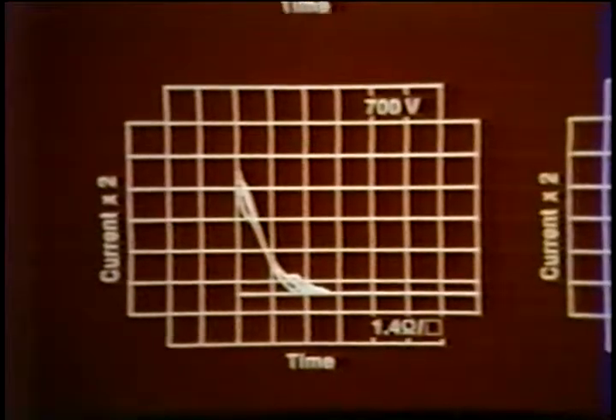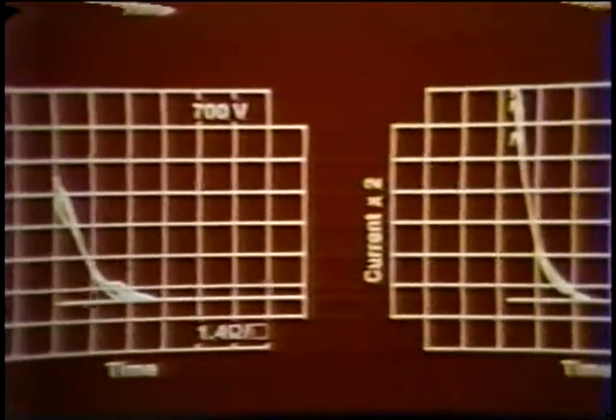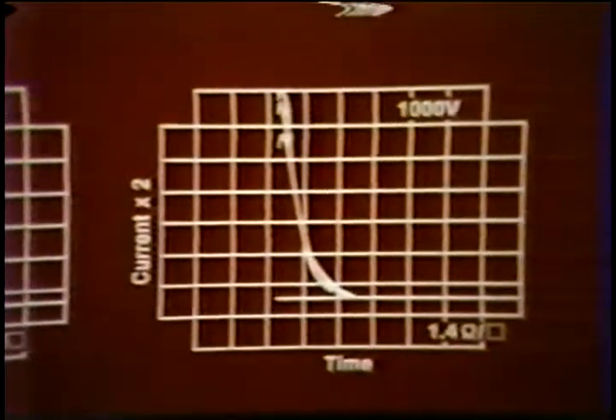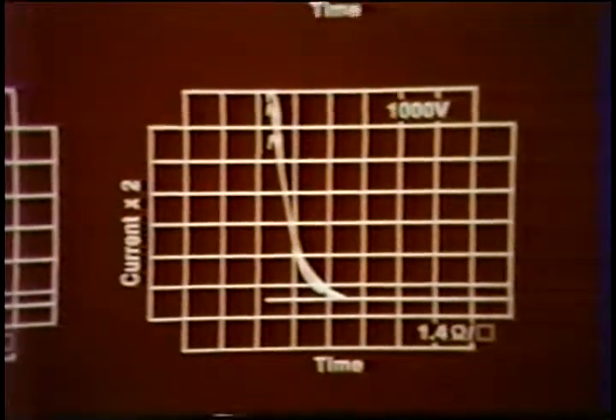As we create clearings at 400, 700, and 1,000 volts, we see that it takes considerably more energy to successfully clear electrodes at the higher voltages. Running several tests of this nature, we can develop a relationship for the clearing energy as a function of the electrode thickness and the applied voltage.